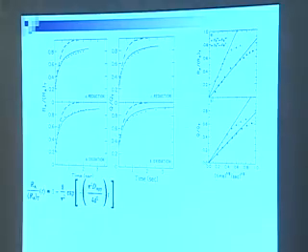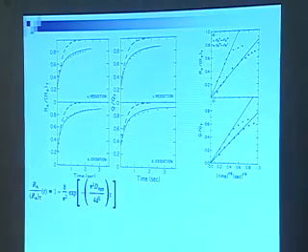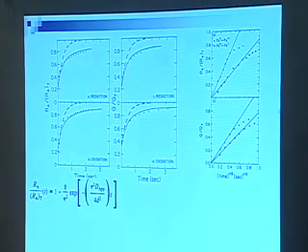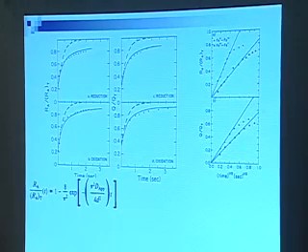So you go through all the things that are here or are hidden in here, and you can't find any suspect, really. What you're left with is the diffusion coefficient. So you say, qualitatively, what this looks like is the diffusion coefficient is changing. It's not a constant, but it's a time-dependent parameter. And it can change the same way. Now, since it's time-dependent, not potential-dependent, it could change in the same direction whether you're doing an oxidation step or a reduction step, right? So that's why you could always overshoot, because your diffusion coefficient isn't what you think it is up here. It's smaller. You put too big a number in.